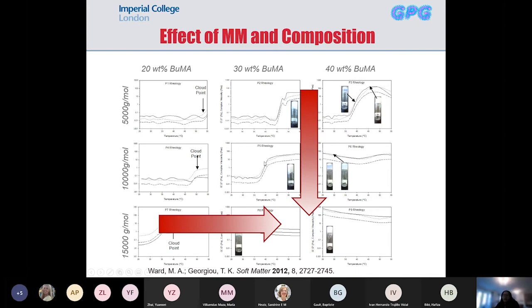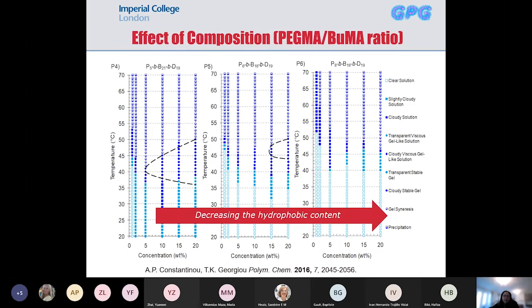So we actually started doing the phase diagrams, which requires, as you can imagine, a significant amount of work for each of the polymers. And what we're interested in is the area within the dotted lines. So this is the gelation area. This is where we get the gel. And in this case, we decrease the hydrophobic component. And you can see that here we don't get the gel. We just get precipitation. Here we get gel at much higher concentrations and temperatures. And here we have a good gelation region for this polymer.